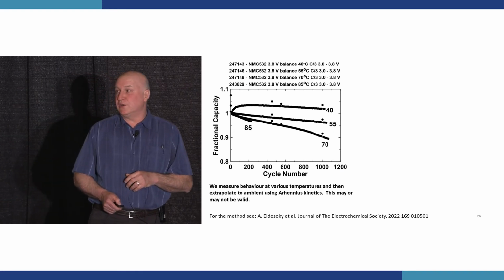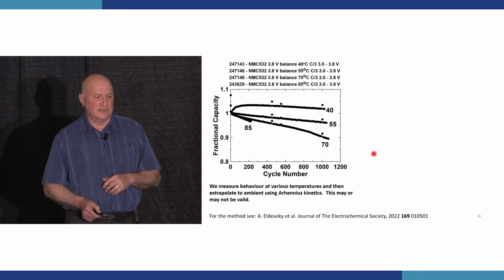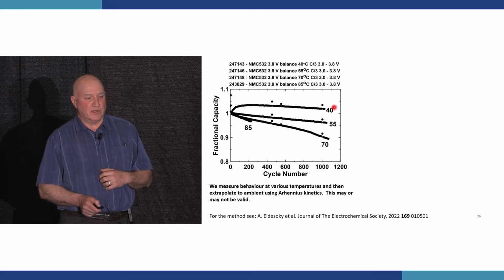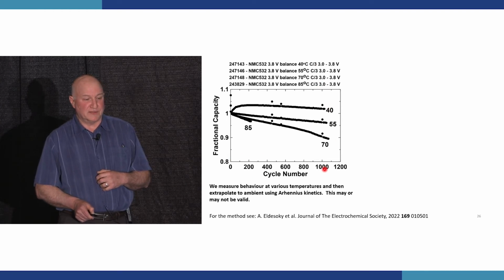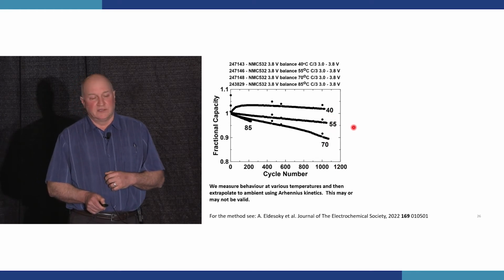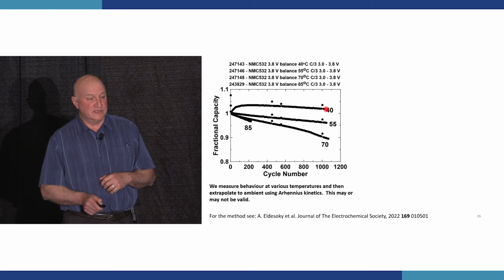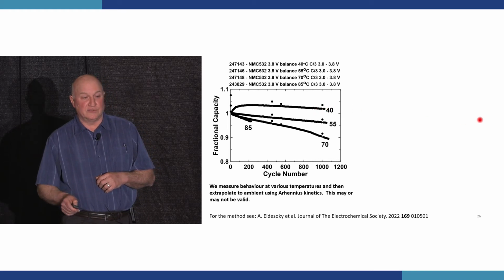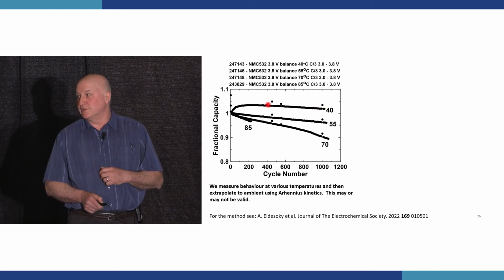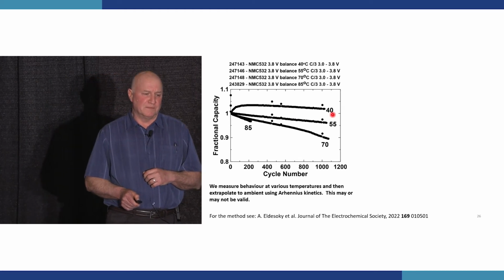So we want to know how long these things are going to last at ambient temperature. So what we do is we do testing at the same 3-hour charge and 3-hour discharge at different temperatures. And what you see here is about 1,000 charge-discharge cycles for cells operated at 70, 55, and 40 degrees C. The cells at 40 degrees C, how long are they going to go? It's beyond the capability of testing them.